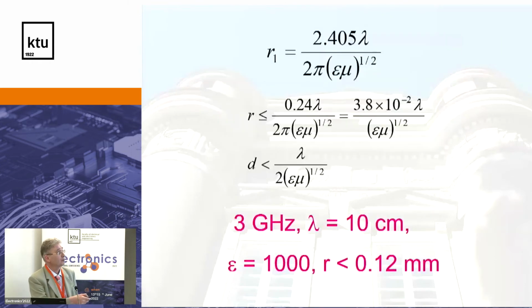This should be the radius where we can assume that the electric field is homogeneous in the whole sample. In that case, the radius of a sample is given by this formula, where lambda is the wavelength of the electromagnetic wave, and epsilon and mu are the parameters of the material. And R should be less than this to have a homogeneous distribution of the electric field.